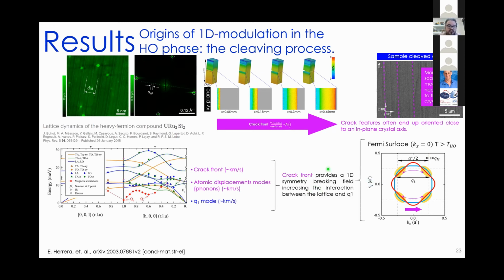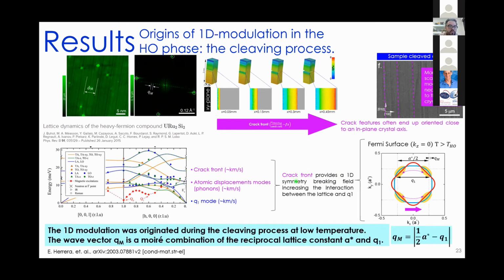So the crack front provides a one-dimensional symmetry breaking field, increasing the interaction between the lattice and Q1. Therefore, we can conclude that the 1D modulation originated during the cleaving process at low temperature, and that the QM vector is a moiré combination of the reciprocal lattice and the Q1 vector. If you want more details, I invite you to check our paper on arXiv.